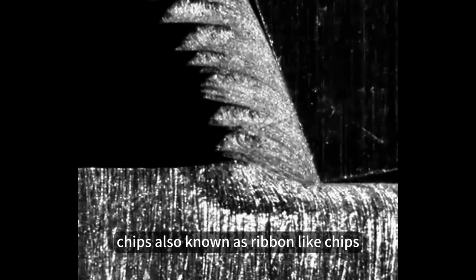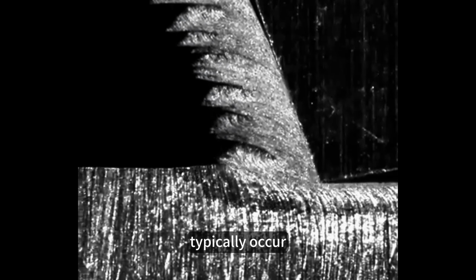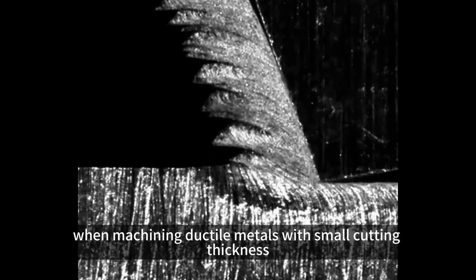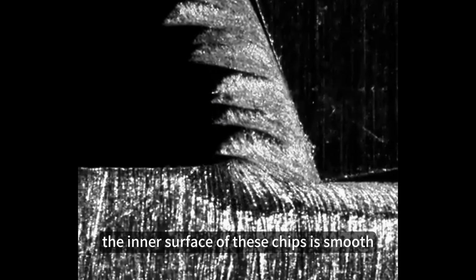01. Continuous chips. Continuous chips, also known as ribbon-like chips, typically occur when machining ductile metals with small cutting thickness, high cutting speed, and a large rake angle on the tool. The cutting process is smooth, with minimal fluctuation in cutting force, resulting in a fine surface finish. The inner surface of these chips is smooth, while the outer surface is rough.